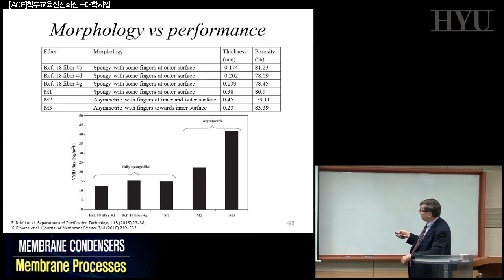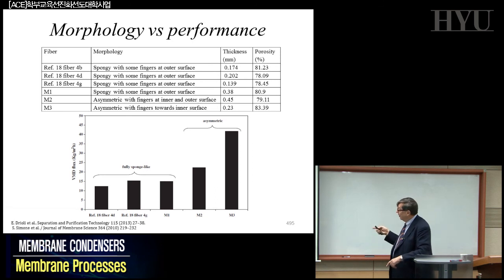What changes very much during this kind of experiment is also the level of porosity. If you have a porosity, in this case, of about 82%, 80%, this can be the best fibers produced today. Basically, they don't exist at commercial level, because if you look at this porosity in terms of mechanical properties, you will find here a tensile strength of 1, 1.5, 2, which is not good enough for microfiltration for sure.